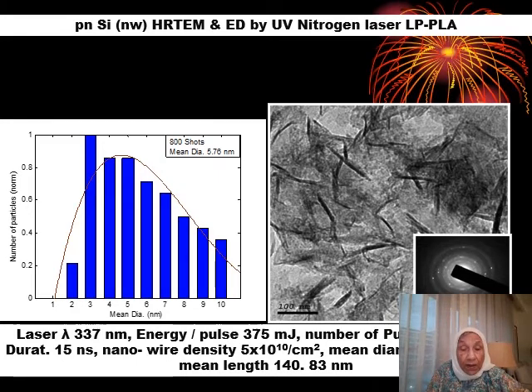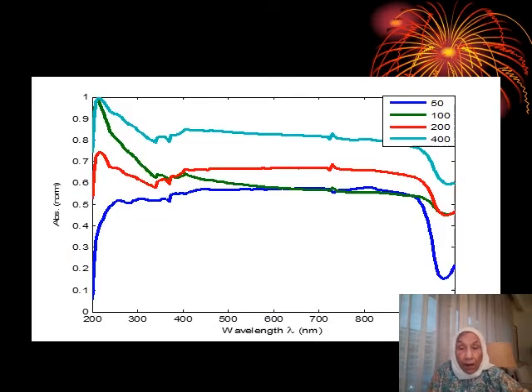So in this case, for irradiation of 15 nanoseconds, we produced nanowire density of 5 10 to 10, and the mean diameter was 5.76 nanometer, and the mean length was 140.83 nanometers.